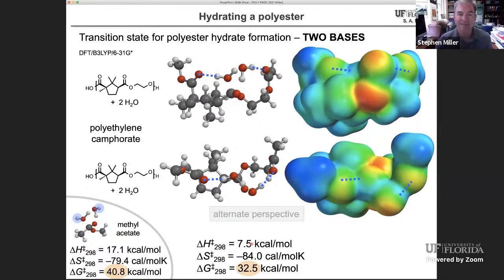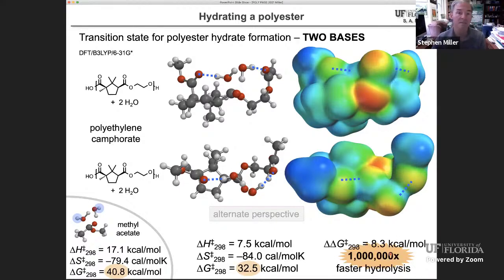You can see the enthalpy barrier is about 10 kcal per mole lower. You do pay some entropy, but again, because it's a polymer, you're not paying all these translational degrees of freedom for the entropy of bringing these flanking ester groups nearby. You just pay a little bit of conformational penalty. So in a lot of ways, this looks like an enzymatic pocket where things are pre-organized. And it turns out that you get a reduction in the delta G double dagger of about 8 kcal per mole, which translates at room temperature to a millionfold increase in the expected rate of hydrolysis. So in some ways, you can call these polymers self-catalyzing. They self-catalyze their own destruction.